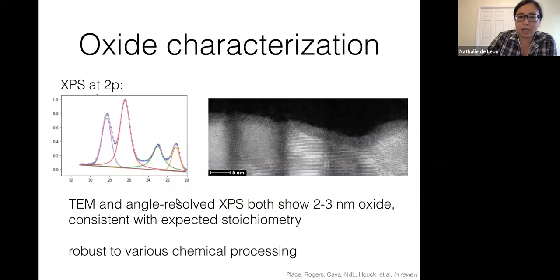If we look at these films very carefully at the oxide layer, we can indeed verify that we get this very well behaved stoichiometric oxide, as Bob predicted. We see that it's basically 2 to 3 nanometers, no matter what we do to these films. It's very, very robust. It's almost like aluminum oxide, where you have this kinetically limited film thickness, and no matter what processing we put it through, we always have this 3 nanometer oxide.